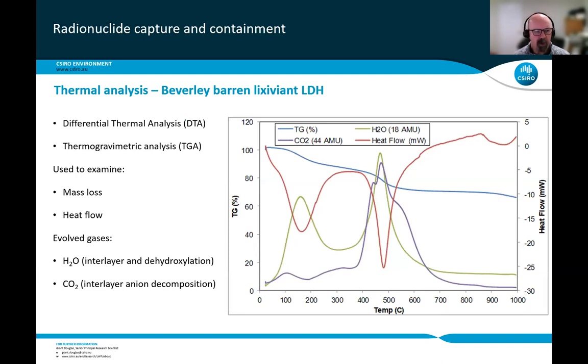So what happens when you heat up the layered double hydroxide that we had from the Beverley mine? Well, we've got here on the right, heating anywhere from 0 to 1,000 degrees. And we looked at differential thermal analysis and thermogravimetric analysis, and that was used to examine mass loss, heat flow, and 2 of the evolved gases, which was water and CO2.